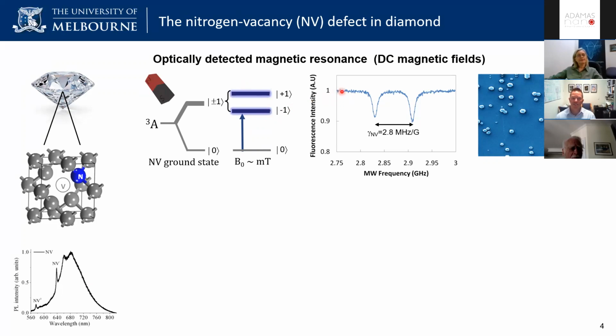And so the protocol for monitoring the position of these energy levels is pretty simple. We just monitor the intensity of the light that's coming back from the NV center as a function of microwave frequency. And when we transition from the 0 to the +1 or the -1 state, we typically see less fluorescence from these +1 and -1 spin states. And so what you'll see is when you make that transition, the fluorescence intensity will decrease. And when we make the transition to the +1 state, we get another decrease. And so this allows us to precisely map the position of these energy levels very accurately using single NV centers, or we can use ensembles of NV centers. It doesn't really matter. The principle is the same.